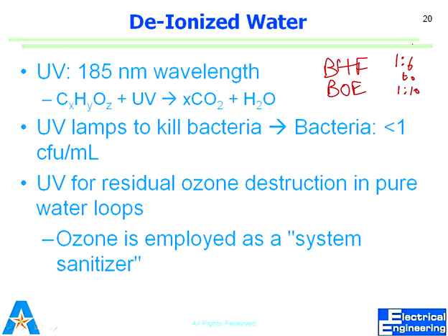Of course, when you dilute, 6 times would be water in there. Say I dip my oxidized wafer into BHF, and I time it, so in 1 minute I'm done with how much etching I want to do, and I take it out. How do I stop the reaction right there? Because some of the BHF is going to be on the wafer. What do I do? Rinse. Put it in a beaker full of DI water. Rinsing will still not be consistent right away, but if I dip it in a beaker full of DI water, it's going to dilute the BHF right away. So I can pretty much control the reaction and stop it right away.